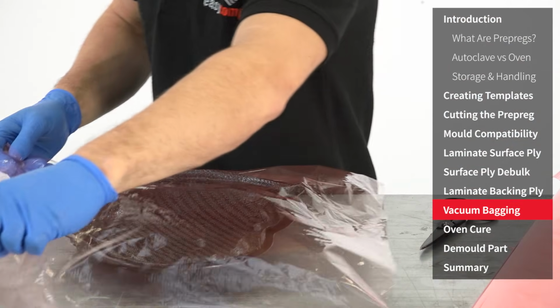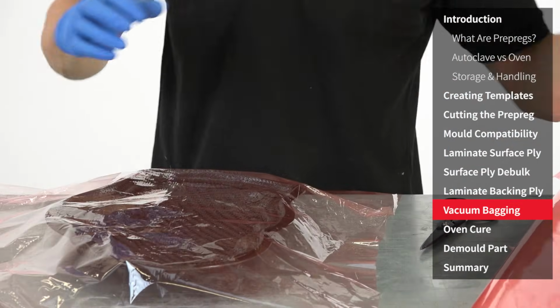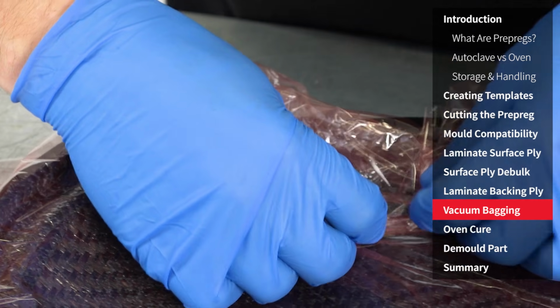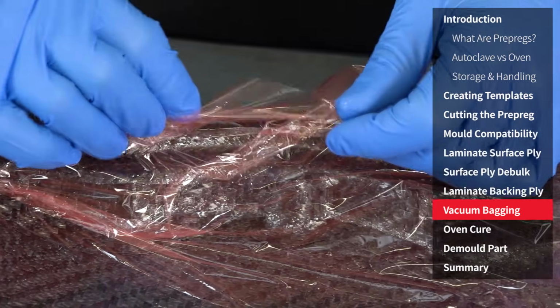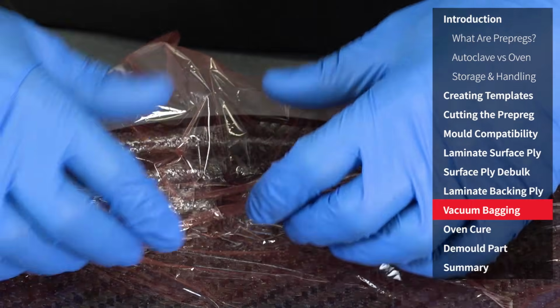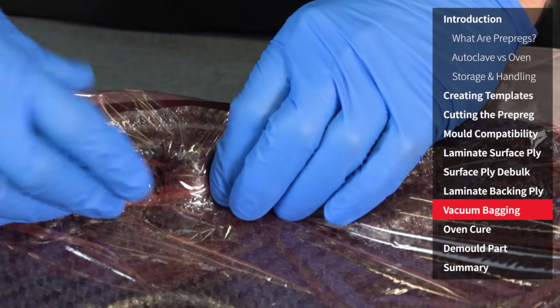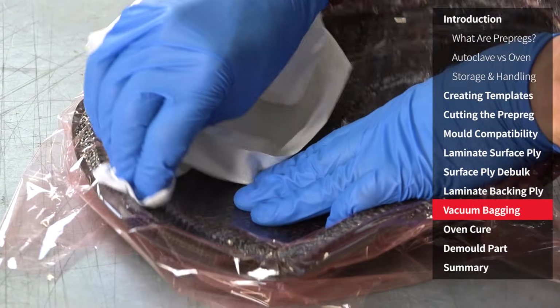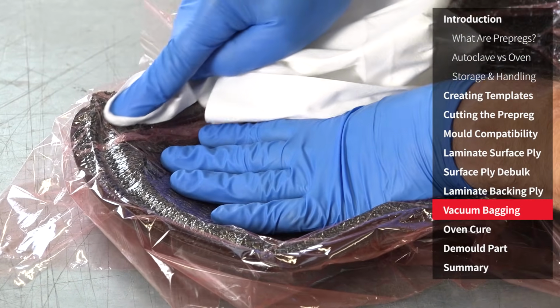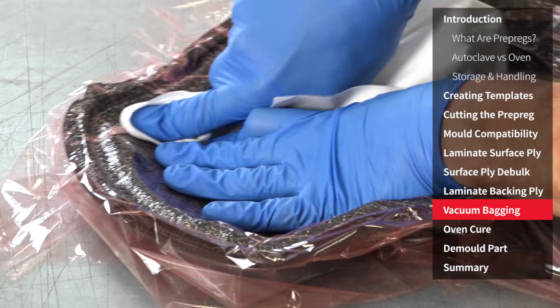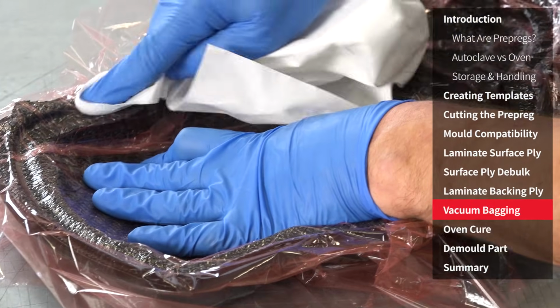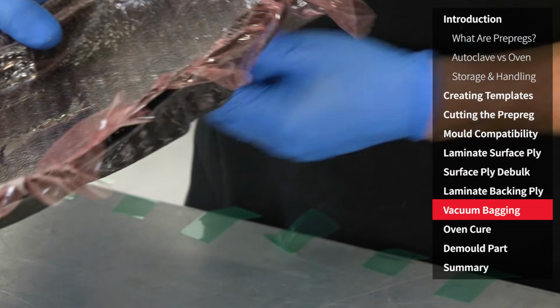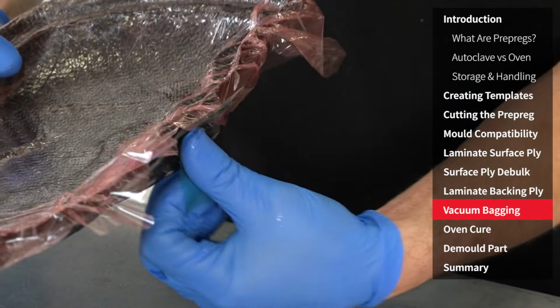With the laminating completed, we can now vacuum bag the part before curing. An unperforated release film should be applied to the laminate. It's actually just as important that this follows every detail and feature as it is with the prepreg itself. Allow for extra film by creasing it in the corners before firmly rubbing it down using a cloth. If needed, the film can be secured in place using flash release tape.